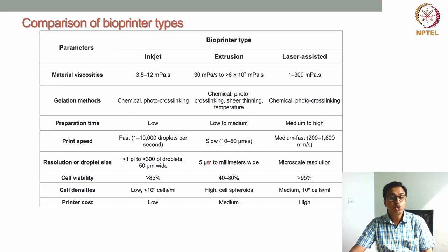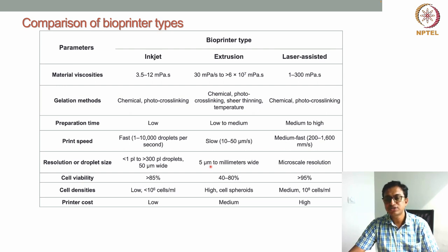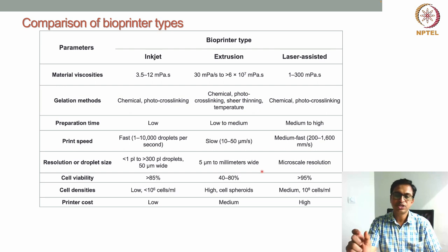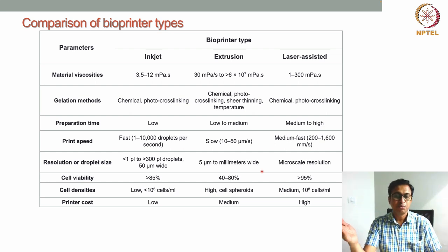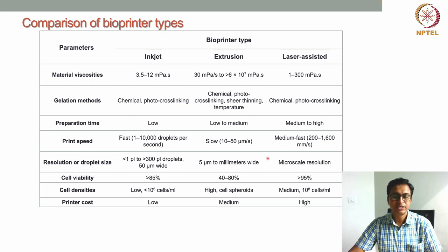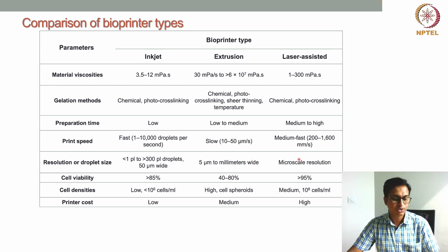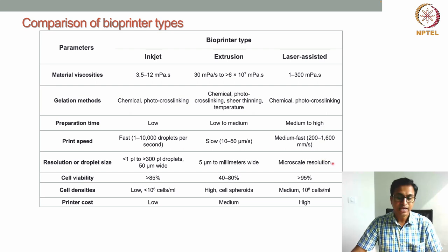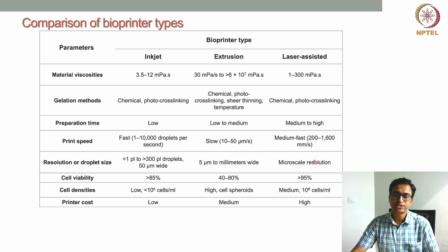In case of extrusion-based bioprinting, resolution is directly dependent on nozzle diameter. Fine nozzles give higher resolution, but cell size is around 10 to 30 microns, so nozzle size cannot be smaller than cellular dimensions. Typically nozzles of 100 microns or more are used for extrusion-based bioprinting, so resolution is not as great as inkjet. For laser-assisted bioprinting, resolution is very high — microscale resolution where droplets containing single cells can be generated.